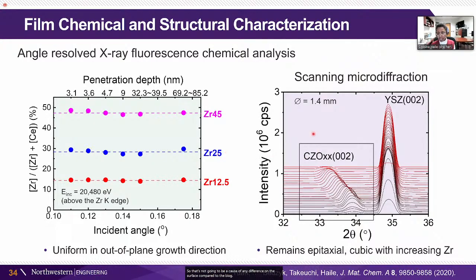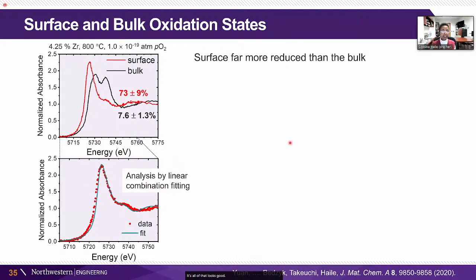So that's not going to be a cause of any difference on the surface compared to the bulk. And we see that in our graded composition film, the material maintains its orientation as we change the zirconium concentration, and a systematic change in the lattice constant, as you expect as you introduce more and more zirconium. So all of that looks good. And here's our XANES result. The most important point here.